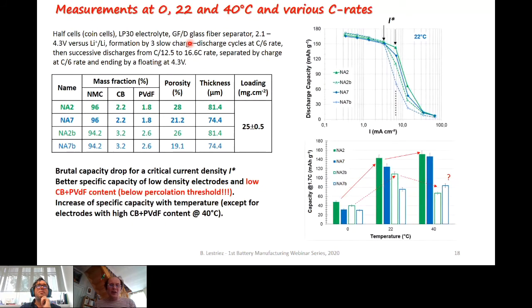So we've done these measurements in half cells, versus lithium, with the LP30 electrolyte and the glass fiber separator. To refresh your mind about the different electrodes, you have Na2 and Na7 in bold and full line here. These are electrodes containing less CB+PVdF compared to Na2b and Na7b, which appear here in dotted lines. And also in green are electrodes with the higher porosity, 28, 26, and in blue with the lower porosity, 21, 19. All electrodes have the same loading, 25 milligram per centimeter square.